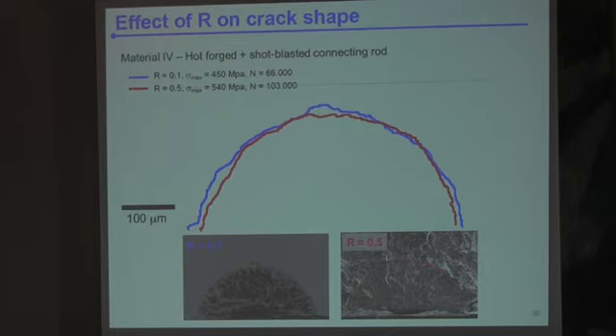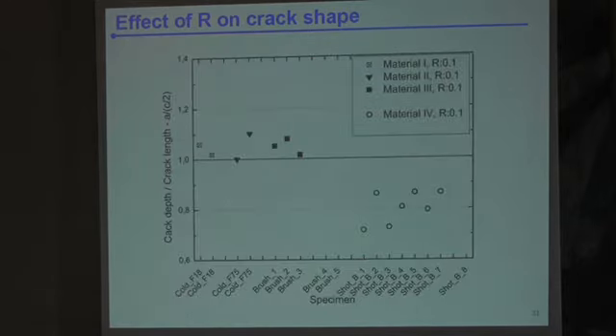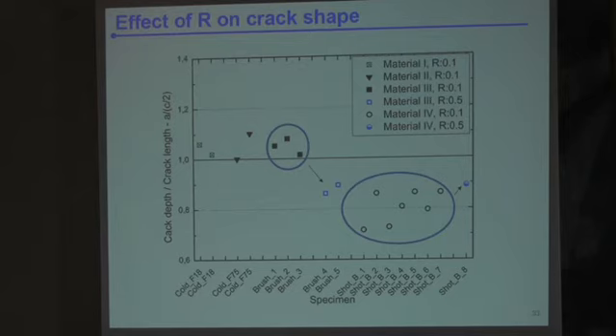So you get an evolution when you move from 0.1 to 0.5 for material 3, and no evolution for material number 4. So if you look at it from this graph, those where the values are equal to 0.1. Now if you go to 0.5 for this material, you went down to a more equilibrium shape for your crack front, while for material number 4, you stay there, right? There is no influence. So what's going on? Well, we believe that this is because of crack closure and the evolution of crack closure around the crack front.